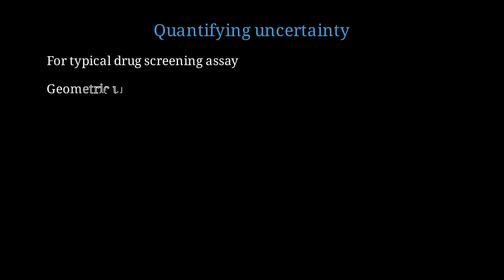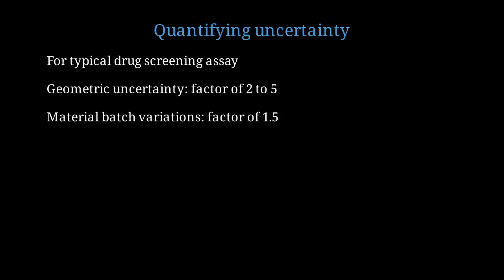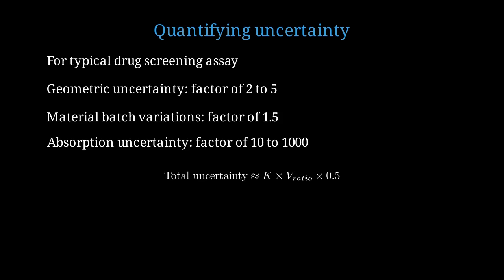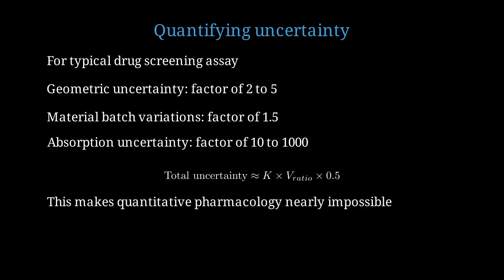Let us quantify the uncertainty introduced by PDMS absorption. For a typical drug screening assay in a PDMS device, geometric variations between devices introduce uncertainty of a factor of 2 to 5. Different batches of PDMS can vary by a factor of 1.5. But absorption uncertainty is a factor of 10 to 1,000, completely dominating all other sources. A rough estimate of total concentration uncertainty is K times the volume ratio times a factor of about 0.5. This makes rigorous quantitative pharmacology nearly impossible in standard PDMS devices.